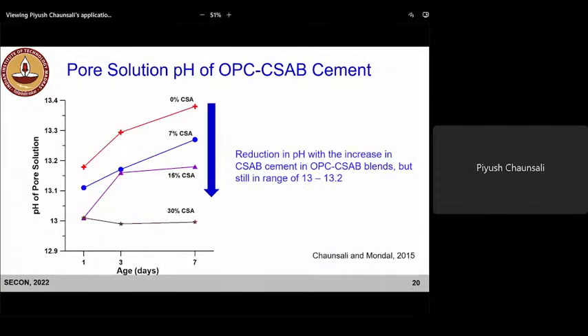Before that, with CSAB cement, there is a reduction in the pH. We know that Portland cement pore solution will have a pH of 13 to 14, but as we add CSA in this case, there is a reduction in the pH. But in this study, we saw that the minimum pH was still around 13. Why is it important?